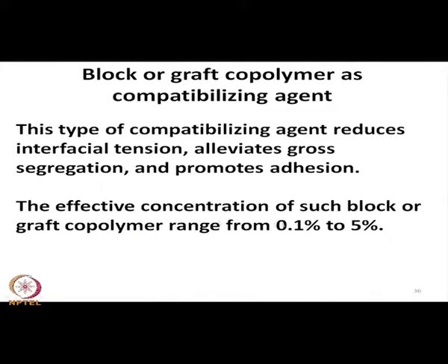The effective concentration of such block or graft copolymers may range from very low amounts, say 0.1% to 5%. So, the presence of this block or graft copolymer produces a miraculous effect in compatibilization of the component polymers in a blend.